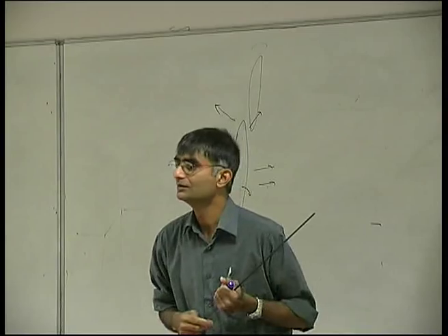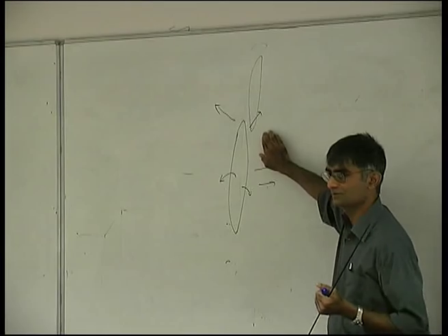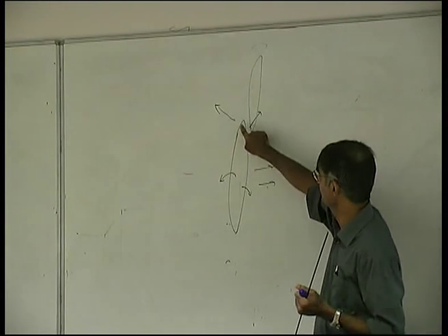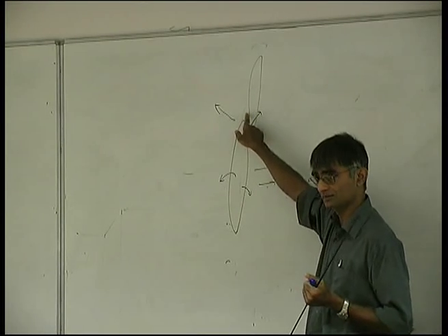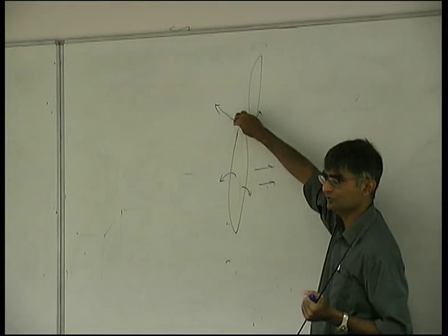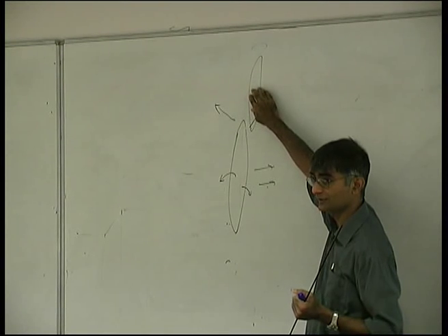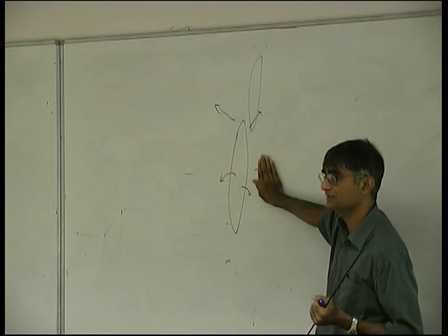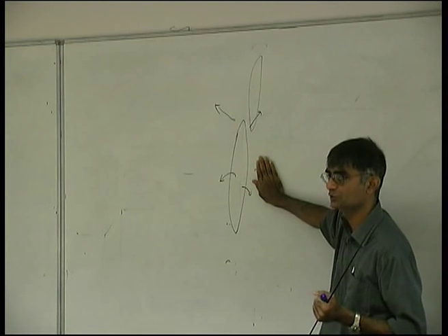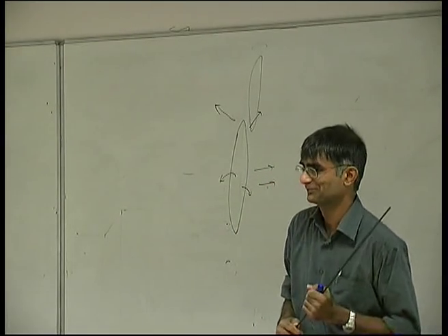Why does it nucleate at the tip? Why not this way? Yeah, exactly. So that is the reason. This is one reason, is that you dissipate carbon much more easily because you're partitioning in many dimensions at the tip than over here. But there is actually another reason, and that is that the strain field near a tip favors the formation of the same orientation. Whereas if you are forming another plate adjacent to it, then you would have to have a different crystallographic orientation, which is more difficult to do. So these are very good questions, actually.